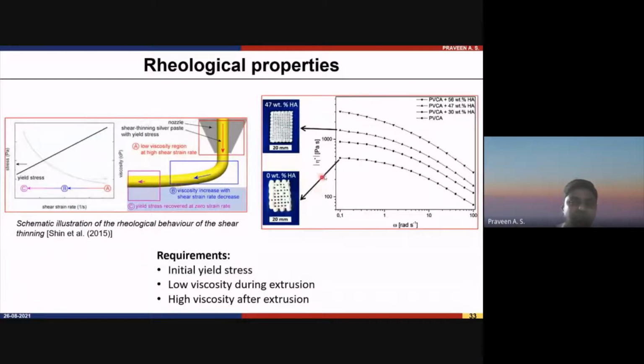See here, because of insufficient ceramic particle content, the structure got distorted. We are not getting the expected shape, and more deposition is taking place here. But with sufficient solid loading, we are able to achieve a good structure like this. So always remember that we should make an ink which has a shear thinning effect, where the viscosity decreases when we apply the strain rate. We can get that from viscosity measurement, or when you go for a rheological study.